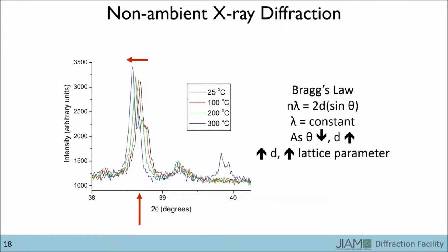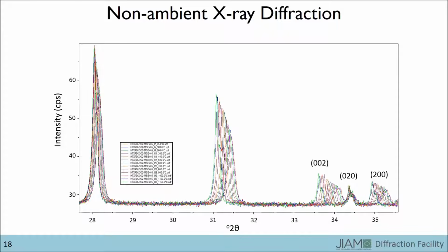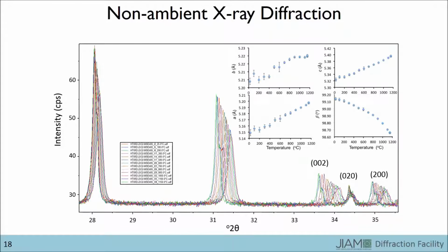From these data, we can determine the values of the lattice parameters as a function of temperature and therefore determine the thermal expansion. This example of a similar experiment on a zirconium oxide sample shows the power of X-ray diffraction in the determination of anisotropic thermal expansion, or thermal expansion that is different for different directions. We can see that the peaks for the 002 and 200 planes shift to lower angles with increasing temperature, while the 020 peak remains relatively unchanged. In a single series of experiments, values for each lattice parameter can be determined for each temperature.